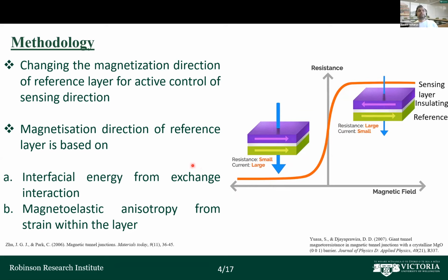So changing the magnetic direction of the reference layer for the active control of the sensing layer is the main idea. As we know, the magnetization direction of the reference layer is based on two things. One is the interfacial energy from the exchange interaction, and the second is the magnetoelastic anisotropy from the strain within that reference layer. So basically, we are going to tune the magnetization property of the reference layer in this experiment.